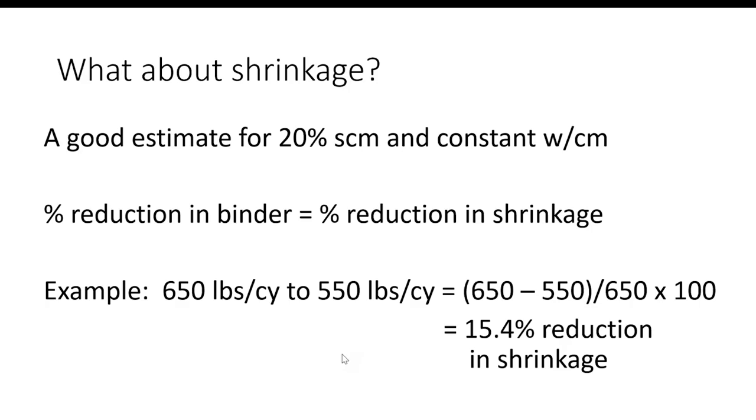Yeah, so that's a great question. Let me tell you about a project that I just did that's about 5 miles from my house. I'm pretty proud of it because it's for the city I live in. We used the Tarantula curve, and we used 600 pounds of total cementitious material with a 20% fly ash replacement. We used 4 pounds per cubic yard of a macro synthetic fiber in that mixture, and we got amazing performance. It was an overlay.